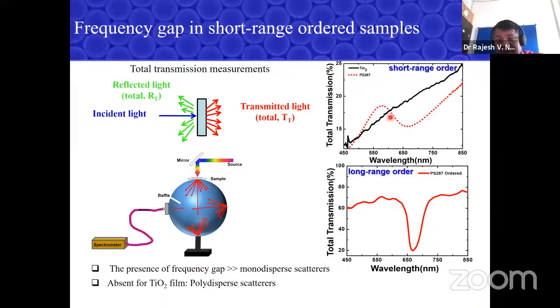So at least we could show that yes, indeed these short range order samples can be made, and this does show a frequency gap similar to the long range ordered one. And this was the first ever demonstration, even though there are huge theory papers right and left published in PRL on correlated scatterers by many groups trying to achieve this kind of sample. Again, experimentally it was really a challenge. How do you make these samples? So this is not the only sample we made. What about the repeatability? What theory can we do?